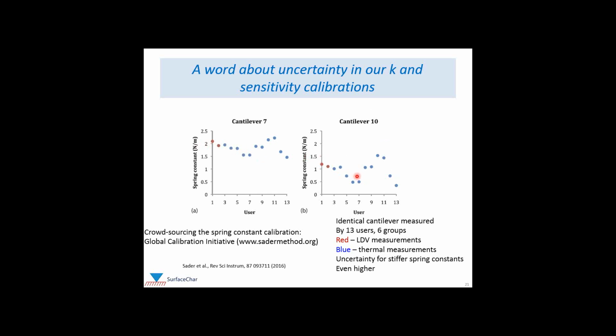And look at the variation. It's quite significant. If we look at this cantilever, we're seeing 50% variation in the spring constant of the identical lever, with more than a 50% variation with some of the thermal measurements and the LDV measurements. So John is trying to promote crowdsourcing of the spring constant calibration. I encourage you to read the paper if you're interested in it. And this was done for spring constants that are fairly soft. So for stiffer spring constants, the uncertainty is even higher.